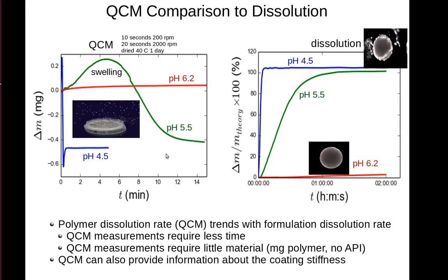Here's an example comparison between QCM measurements and dissolution. On the left is mass versus time for a QCM measurement at varying pHs, and on the right is mass versus time for a traditional dissolution measurement. If we look at the QCM measurement, at a pH of 4.5, we see the polymer film swells and then rapidly dissolves within under a minute.